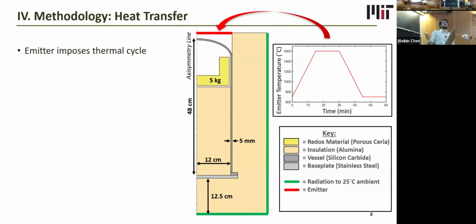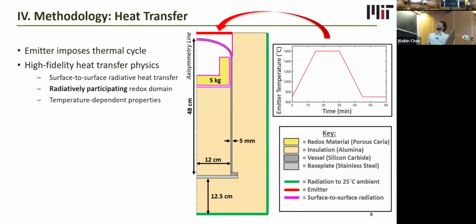So in order to simulate a thermal cycle, we impose a diffuse emitting boundary condition with a sample temperature profile that goes from 700 to 1600 degrees Celsius, some slight underheat and overheat. This is not meant to perfectly simulate what the reactor would experience in a reactor train system, but it is meant to provide a baseline thermal cycle to see how the reactor responds to thermal cycling and compare different reactor designs. It uses high fidelity heat transfer physics with surface to surface radiative heat transfer and assumes that the redox material is that same porous ceria that Remo was talking about before. We model this using the P1 approximation.